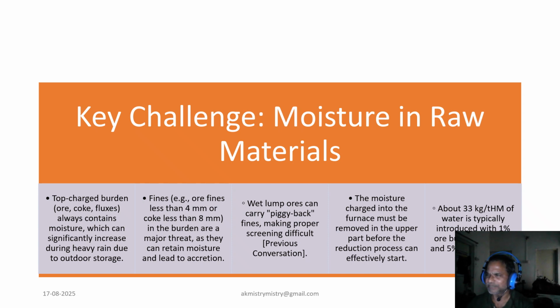A major threat comes from fines such as ore fines less than 4 mm or coke fines less than 6 to 8 mm, because they can retain moisture and lead to accretion within the furnace. Even wet lump ore can carry piggy back fines, making proper screening very difficult. Crucially, any moisture charged into the furnace must be removed in the upper part before the reduction processes can effectively begin.